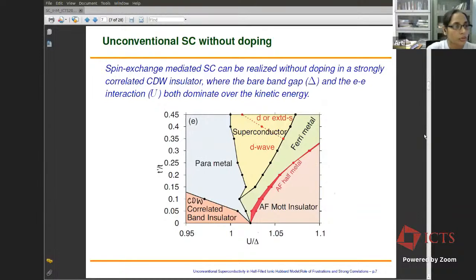So what I'm going to show you today is superconductivity in a half-filled ionic Hubbard model, where the system is strongly correlated and is at half filling, but still the system has enough charge dynamics such that once you frustrate the magnetic order, the superconducting phase can be realized. And the interesting feature about the superconducting phase is that on one side, it is sandwiched by a charge density wave band insulator. On the other side, you have an antiferromagnetic Mott insulator. And once we have enough frustration against the magnetic order and the system has enough quasiparticles, the system shows superconductivity.